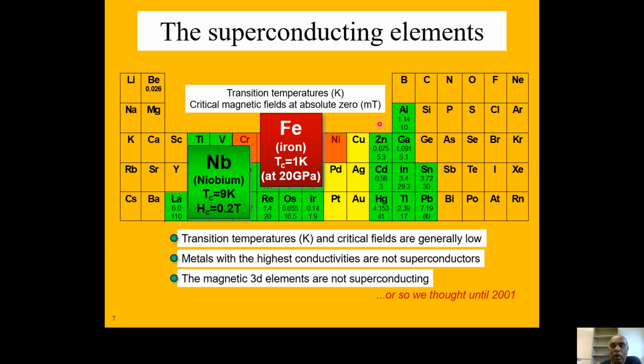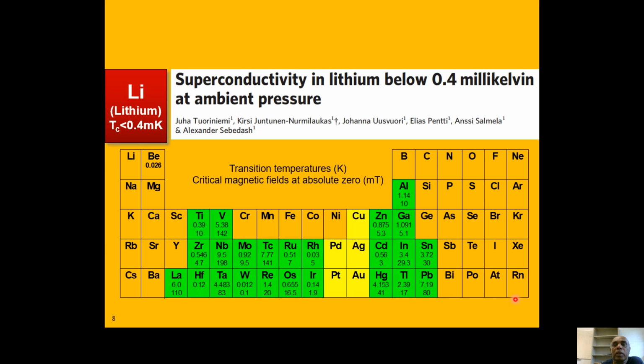Later they found superconductivity in iron, with Tc about 1K, but at very high pressure, about 20 gigapascal. This was discovered in 2001. Then later they found superconductivity even in lithium, though with very low Tc, about 0.1 to 0.4 millikelvin. So even lithium became superconducting.